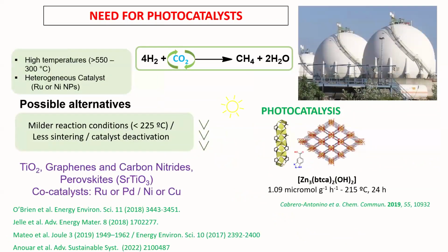Obviously, this reaction has been reported in the literature employing very high temperatures. Typically people use more than 550 degrees centigrade, and also heterogeneous catalysts like ruthenium or nickel nanoparticles. This is well known as the Sabatier reaction. One of the possible alternatives is to reduce the temperature or employ milder reaction conditions, typically reducing the temperature or the pressure of hydrogen gas.